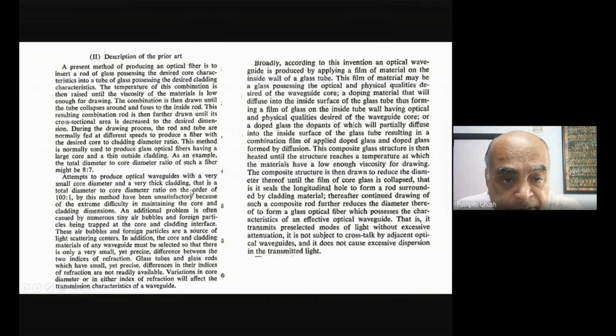Attempts to produce optical waveguides with a very small core diameter and a very thick cladding, that is a total diameter to core diameter ratio on the order of 100:1, by this method have been unsatisfactory because of the extreme difficulty in maintaining the core and cladding dimensions. An additional problem is often caused by numerous tiny air bubbles and foreign particles being trapped at the core and cladding interface. These air bubbles and foreign particles are a source of light scattering centers. So you can imagine, if the light is going to scatter, then I'm going to have tremendous attenuation of the light. So that is not going to be useful.